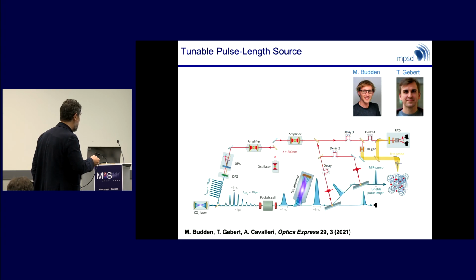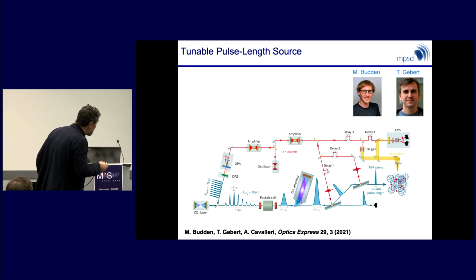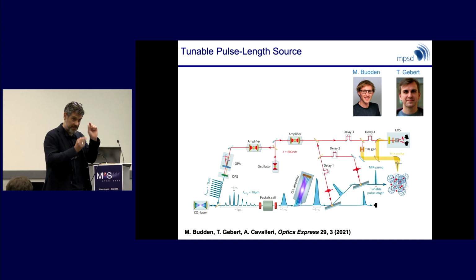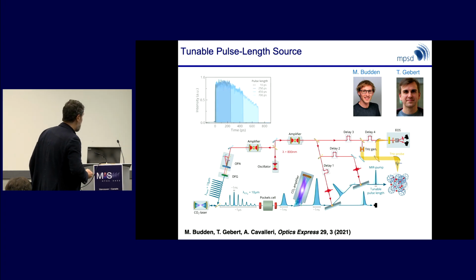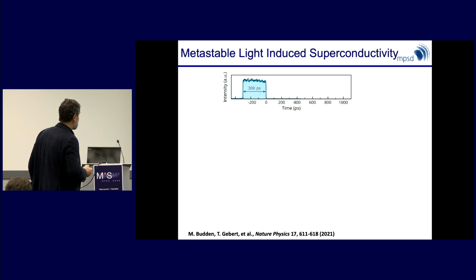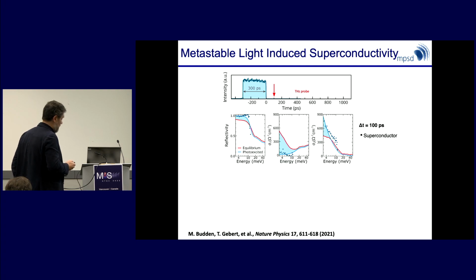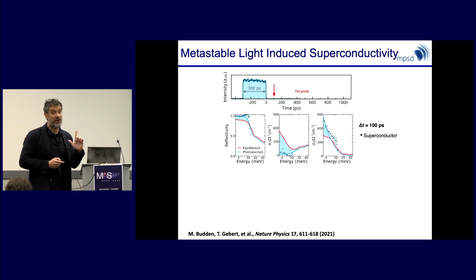This is a big laser that Matthias Budden and Thomas Gebert built based on CO2 lasers and various, seeded by a femtosecond laser, that allows us to do exactly the same experiment that we did before. This is the Terahertz probe, and instead of pumping it with a 100 femtosecond pulse, I can now make my pulse tunable between 1 picosecond and a nanosecond. So basically, now the experiment is done at 10 hertz instead of a kilohertz. So the signal to noise has gotten a little bit worse.